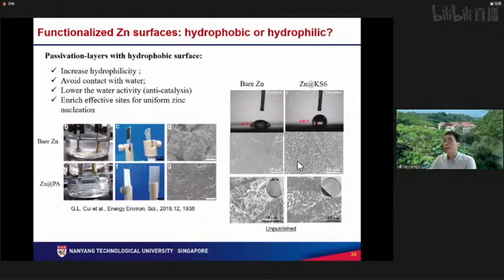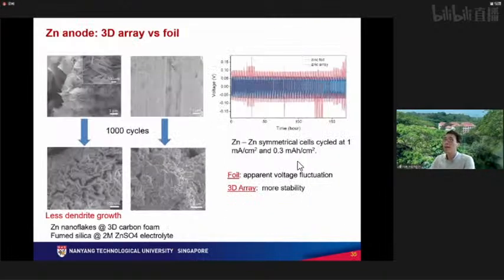This is the effect demonstrated by Cui Guanglei in this work. They increase the density of the nucleation sites, so have a more uniform deposition. And another effect, we think that maybe this passivation-layer-dependent interface chemistry may lower the water activities. So it's sort of an anti-catalysis effect. For example, in 2018, again, we used a three-dimensional zinc and found that compared to zinc foil, the surface does not have very large spherical agglomerations of zinc compared to the zinc foils. And the symmetrical cell also shows a very stable voltage profile.